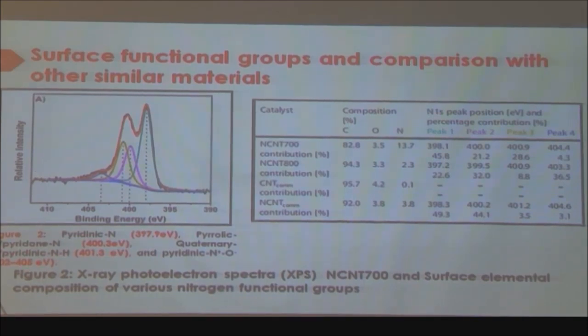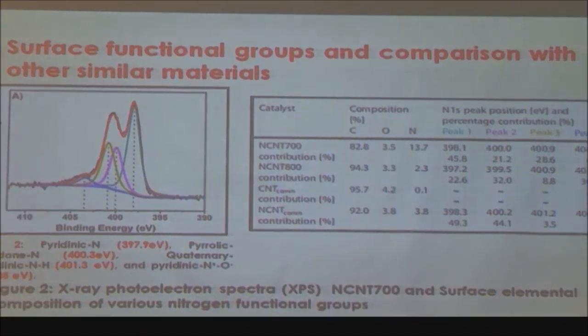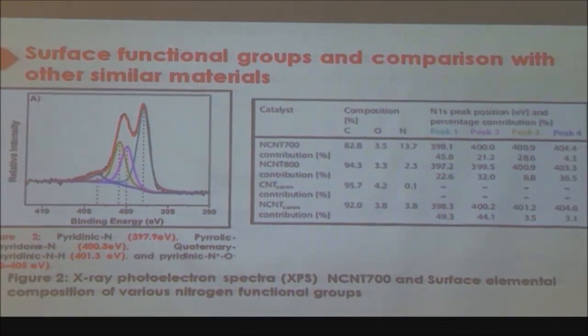For those who don't know what XPS is, XPS is a technique that tells us what type of atoms are present on a material, so the chemical composition of a material. What type of atoms are there can be analyzed through XPS. So we do the XPS and we look for nitrogen. Different types of nitrogen have different binding energies. Based on those binding energies, we are able to identify which type of nitrogen is present on the surface. So we identify pyridinic type, pyrrolic type, quaternary nitrogen, as well as NO on the surface of this material.